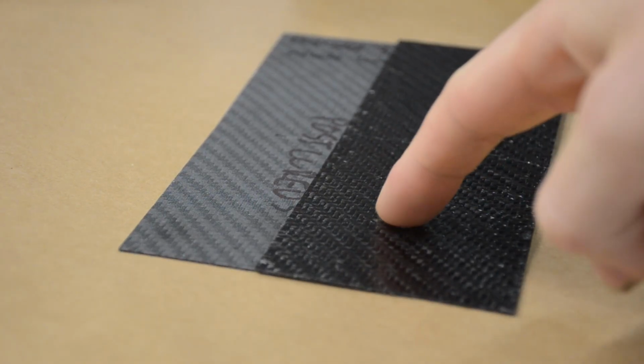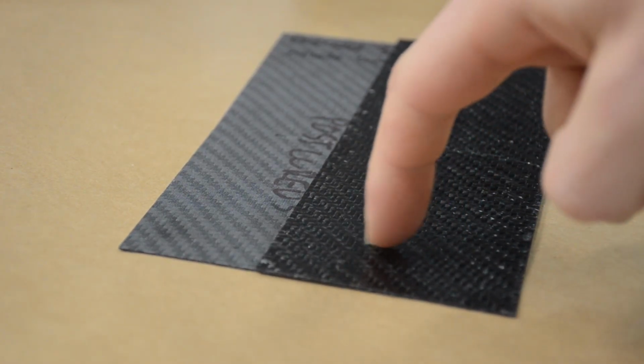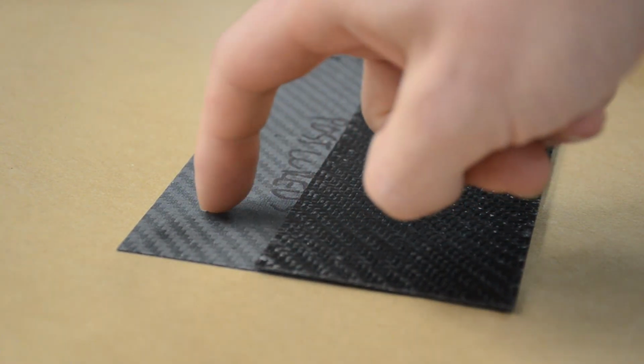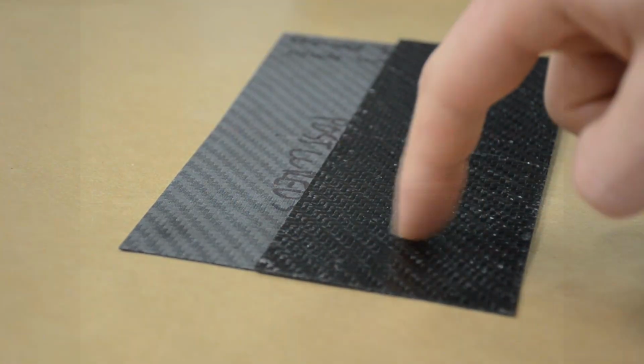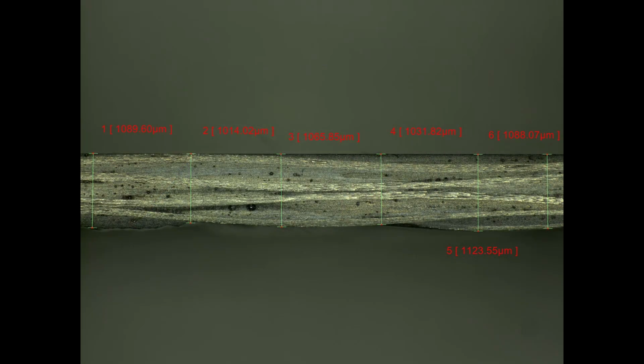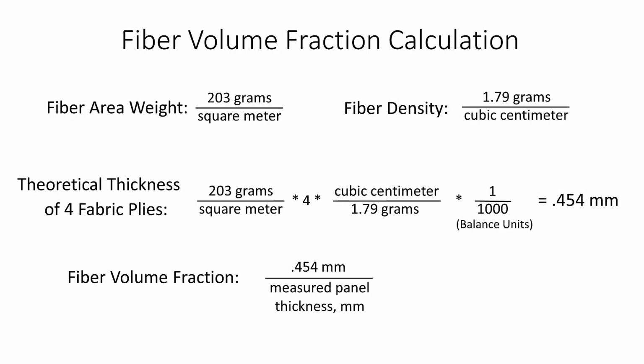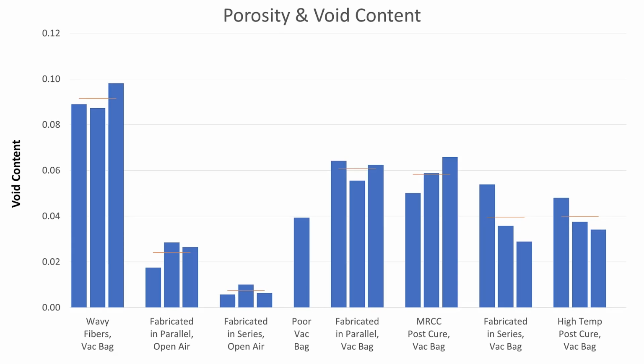Since woven fabric was used, the samples had a slightly rippled surface which has different thicknesses in different areas. Thickness measurements were taken in multiple areas and a portion of the sample thicknesses were checked for agreement with thickness measurements taken with a microscope. The porosity and void content of the samples was calculated by comparing the expected sample thicknesses based on the fiber and total mass and the component densities to the measured sample thicknesses.